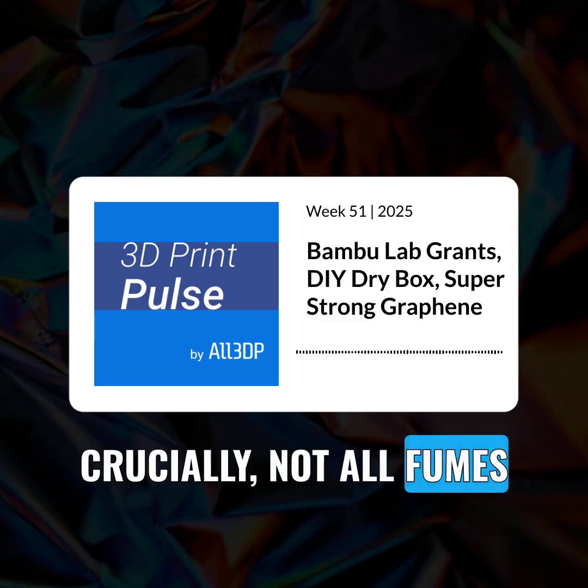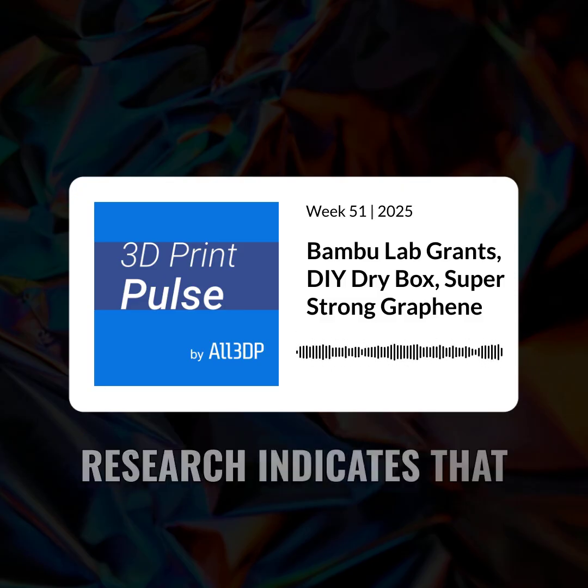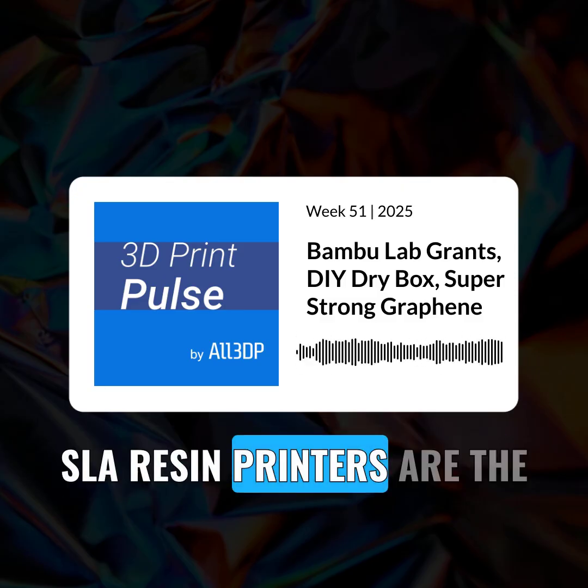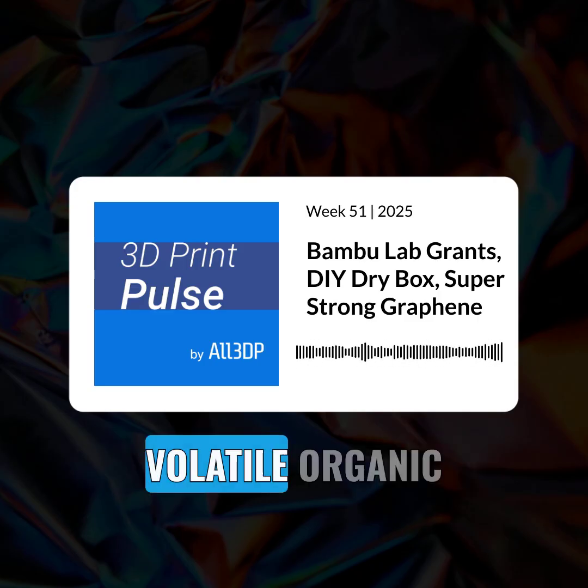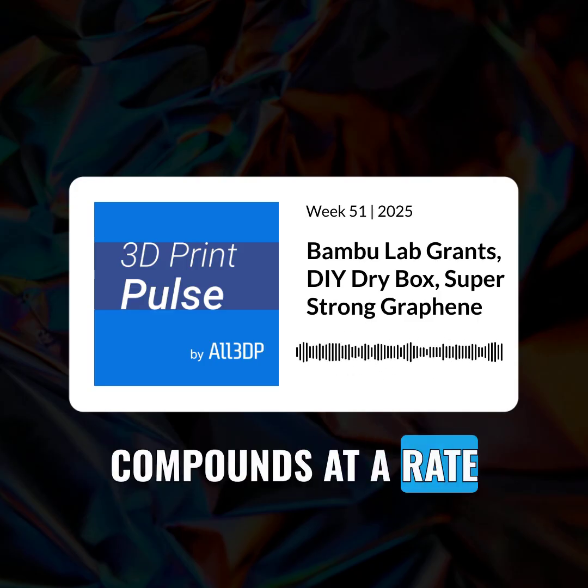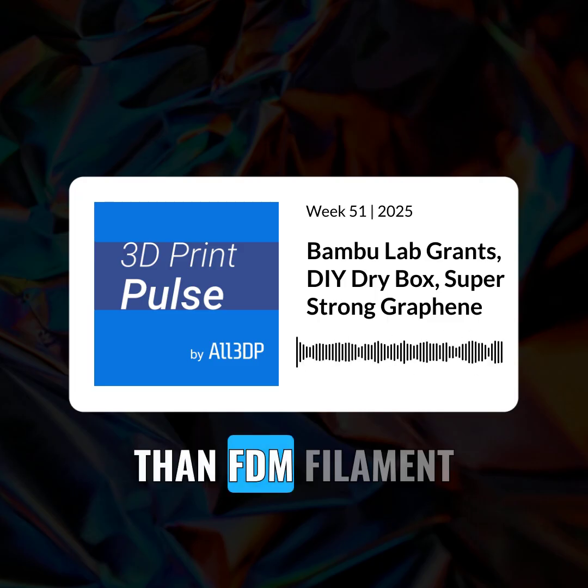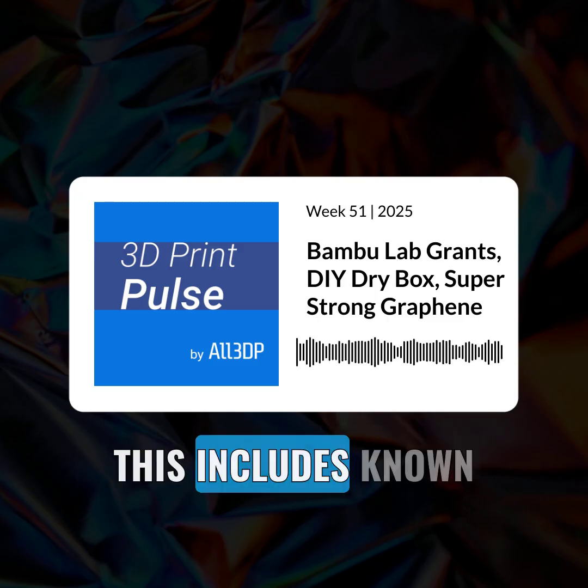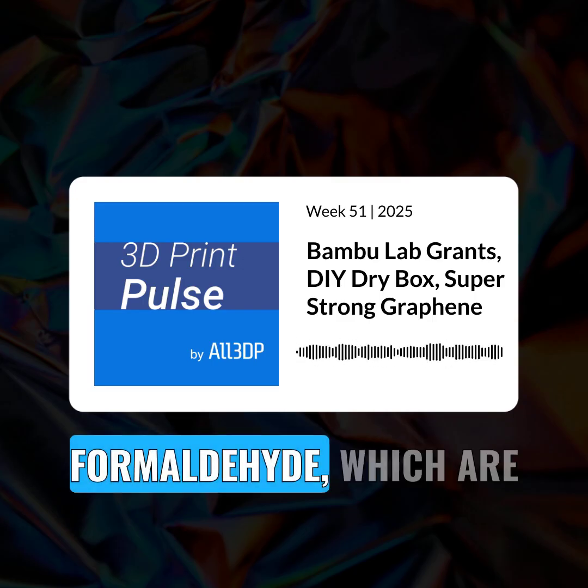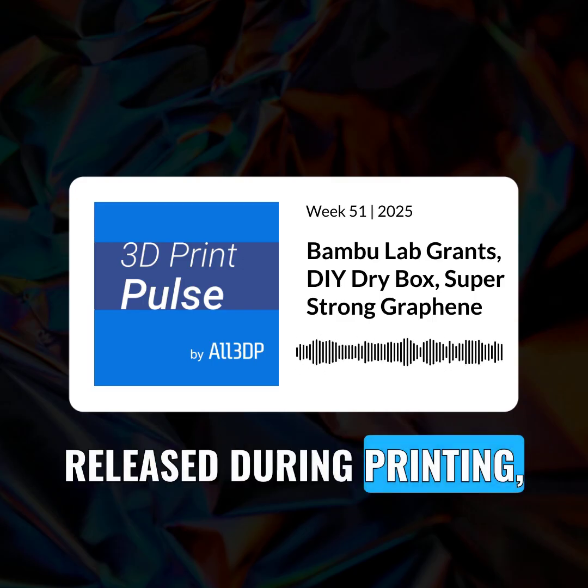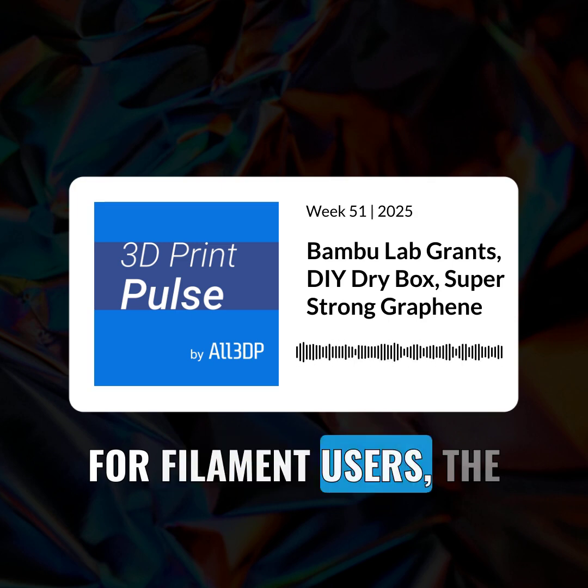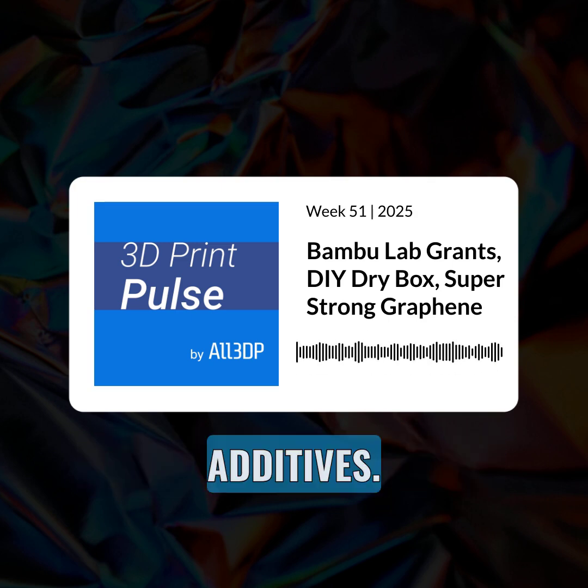Crucially, not all fumes are created equal. Research indicates that SLA resin printers are the heavy hitters, emitting volatile organic compounds at a rate 3 to 6 times higher than FDM filament printers. This includes known carcinogens like formaldehyde, which are released during printing and curing. For filament users, the danger often lies in the additives.